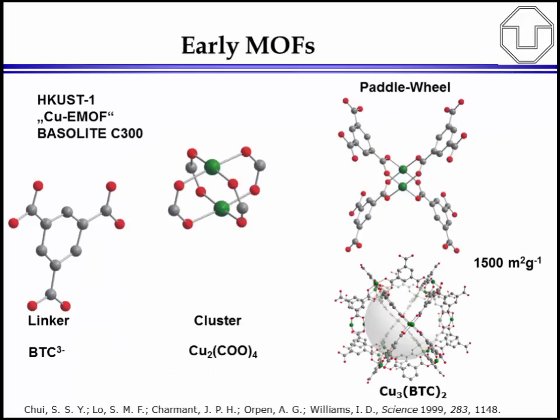So in the next slide I show a metal organic framework that was discovered very early, the HKUST-1 structure, which is also commercially available from BASF, the Basolite structure. This is nowadays a very common MOF material, about 1,500 square meters per gram surface area, medium-sized pores. It's a hydrophilic MOF material that is quite useful for a number of applications, because it also has open metal sites and can adsorb different types of gases.